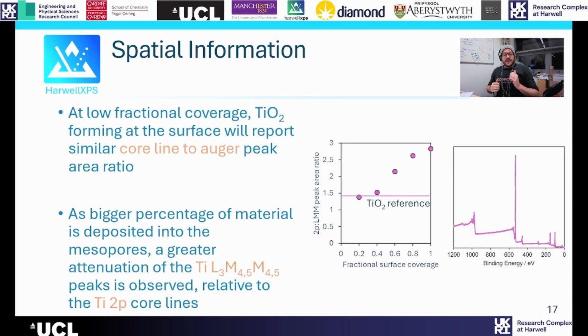When we look at the area ratio of these two peaks at low fractional coverages, this ratio pretty closely matches a reference of pure TiO2, but as we increase the coverage, the amount of titanium 2p relative to the Auger increases, and this is attributed to a difference in how much of our surface is coated by titania versus how much of our inner pores are coated by titania. Because in our low coverage example, if we have the majority of our titania on the outer surface only, we will get a very similar ratio to a pure titanium reference, because there should be no difference in how much of the signal is coming from the surface versus the pores.